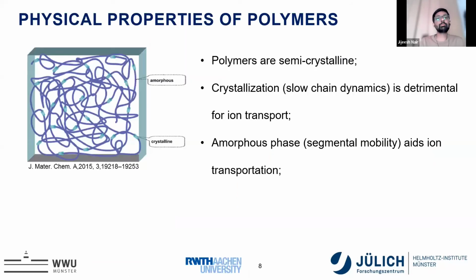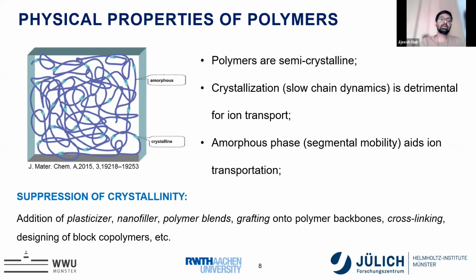So what are the physical properties we require for a polymer electrolyte in this respect? For example, if you know polymers in general, those are semi-crystalline materials. They have a crystalline phase and an amorphous phase. And the crystalline phase cannot conduct, or conducts very little, the positive charge or lithium. However, the amorphous system, because of its segmental mobility or lower glass transition temperature, can help the ionic mobility.